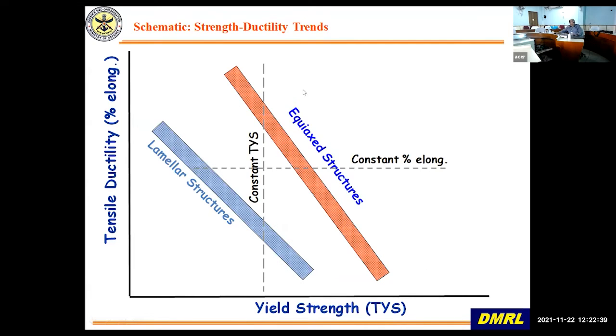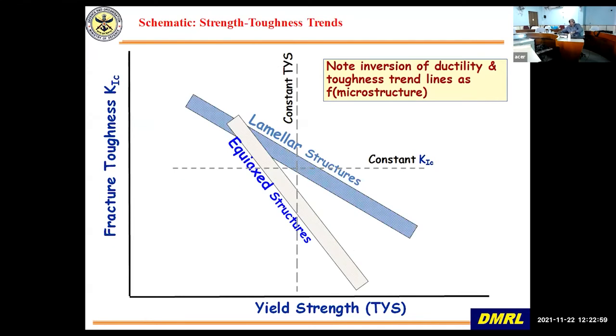Equiaxed microstructure is better at comparable yield strength. The equiaxed structure has higher ductility as compared to lamellar microstructure. Lamellar microstructure normally has lower ductility, but lamellar microstructures are better for creep kind of applications. Then as far as fracture toughness versus yield strength goes, the lamellar microstructure is better off for fracture toughness, and for equiaxed microstructure fracture toughness is slightly compromised.